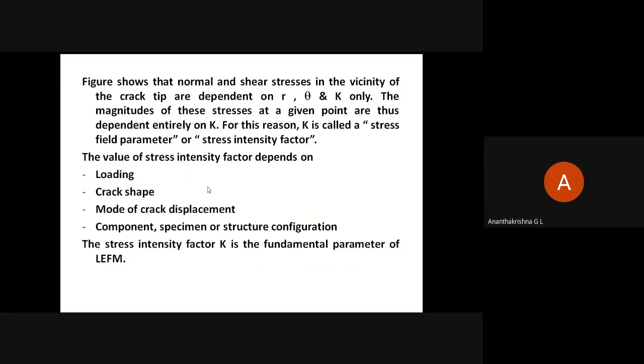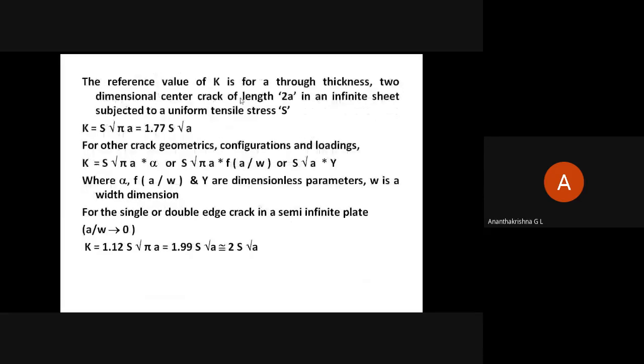So the stress intensity factor depends upon these four parameters. Okay, and it is fundamental for the LEFM approach. Then after that, we learned that for a through thickness crack, K is given by 1.77 S root A, that is, A is crack length, S is stress, okay?